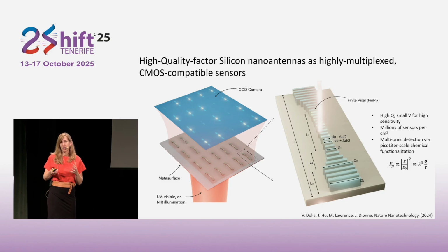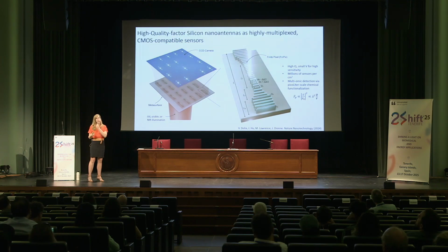It's basically silicon nanoresonators, in this case silicon bars, that have slightly different widths in this cavity region, which here I've labeled as L1. And then we have basically a tapered photonic crystal mirror that makes the structure appear as if it's infinitely long, even though it's just going to be a few microns long, and then kind of this padding region. And what we do is take these silicon bars, we use CMOS-compatible fabrication processes to pattern these on a substrate. We illuminate anywhere from the visible to the near-infrared. And then what we do is in the far field on a CCD camera, basically detect the Raman scattering signal.